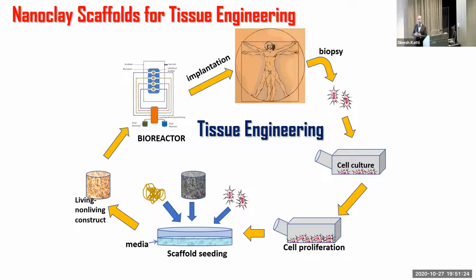And so we were working on bone tissue engineering. We wanted to regenerate human bone. And so we were working with polymeric scaffolds. These scaffolds were very soft, and we wanted to increase the strength and stiffness of these materials. So obviously, we were working with polymer clay nanocomposites. We said, hey, how about we take the nanoclays and put them in these polymers, and you will have much stiffer and stronger scaffolds. But there was a problem. The problem was the chemicals that were used to make nanoclays were too toxic. So that won't work here.